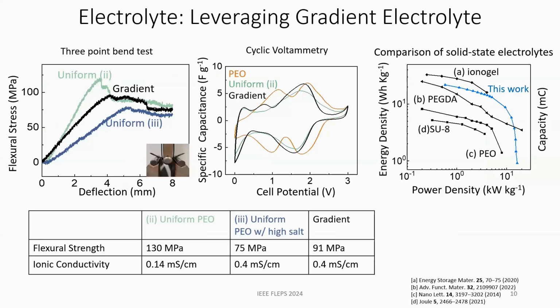Next, we can look at the electrochemical and mechanical properties. So this green line is our uniform PEO epoxy solution. So this has the highest flexural strength of 130 megapascals, but a low ionic conductivity. And the blue line is our high salt ratio, which has the lowest flexural strength, but high conductivity of 0.4 millisiemens per centimeter. And our gradient electrolyte keeps the same conductivity and then reaches a higher flexural strength of 91 megapascals. And then here is our PEO liquid electrolyte in the orange line.